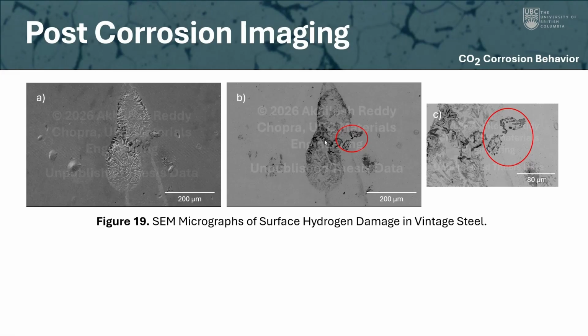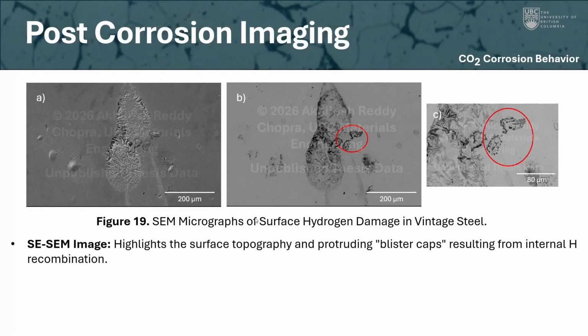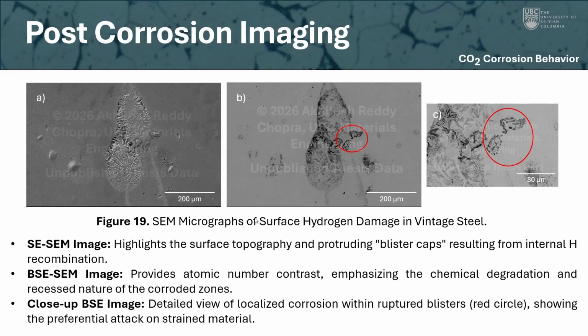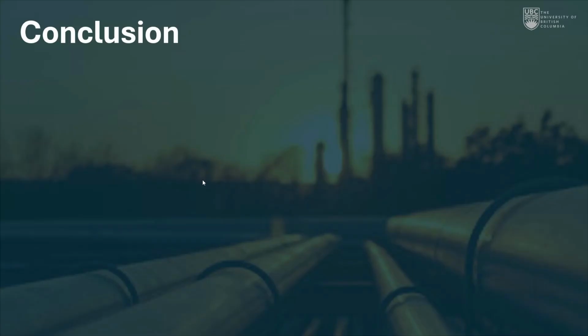And then in figure C, those two areas were blisters. So those were distinct blisters that were formed, and we can see around the periphery, around the perimeter, as well as on the blister cap, both have been attacked locally. And so this is quite interesting for me to see how hydrogen can in fact accelerate corrosion in steel.